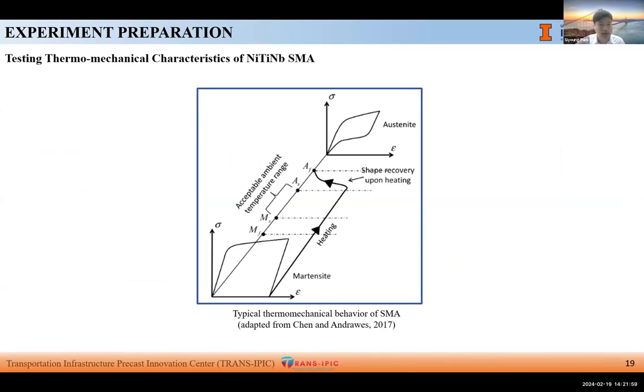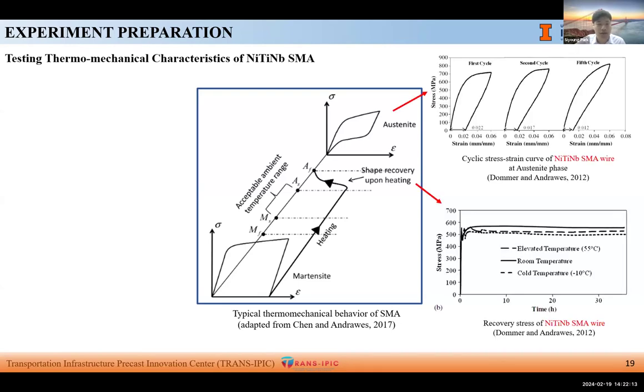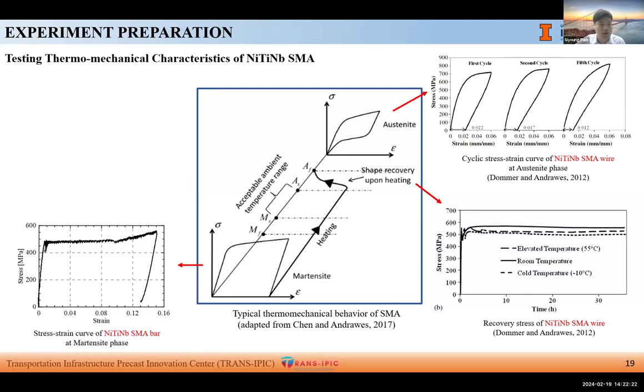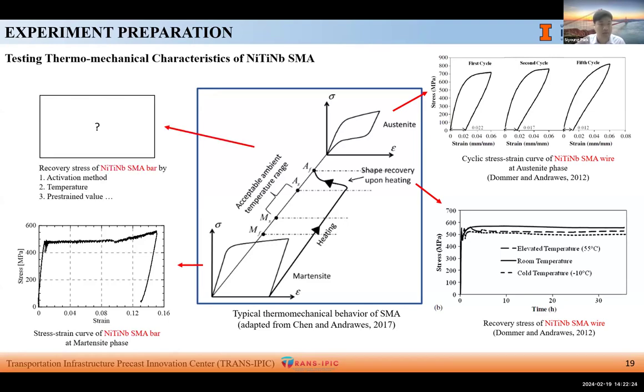The thermomechanical characteristics of nickel titanium niobium SMA is also under investigation. As SMA has different attributes by temperature, monotonic and cyclic testing are in progress. There was a previous study of nickel titanium niobium SMA wire in austenite phase in terms of pre-straining and activating. Now we are focusing on the martensite phase to early activation from martensite phase to austenite phase. Activation method, temperature, and pre-strain value can be variables for determining the recovery stress, which should have an effect on the concrete, so these studies are going on.